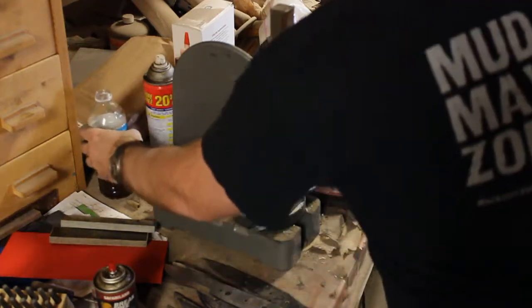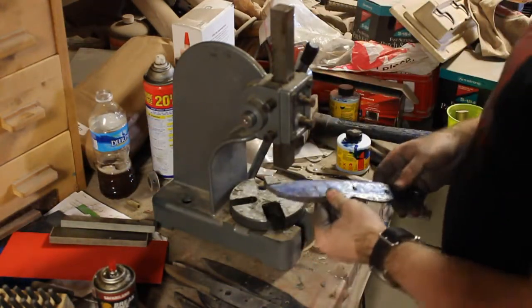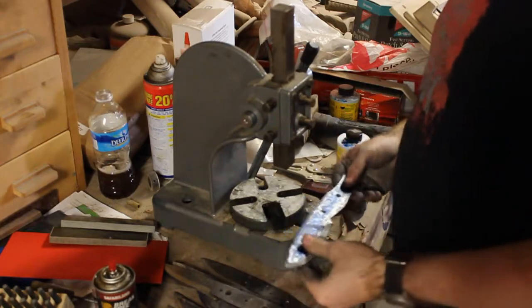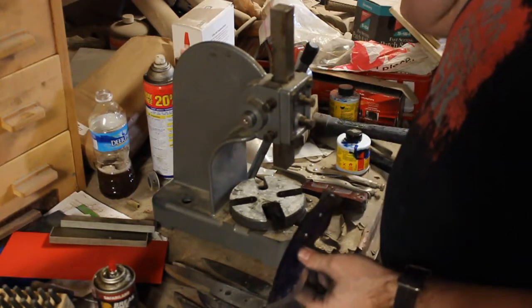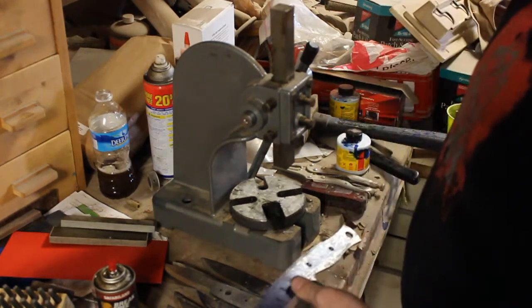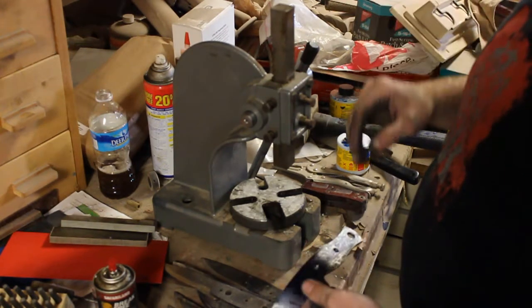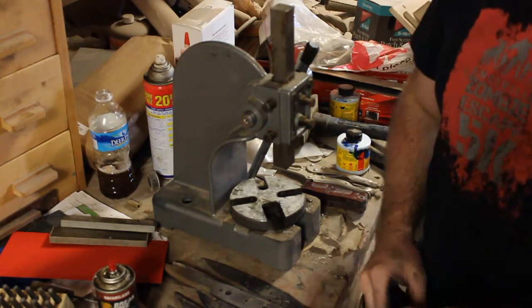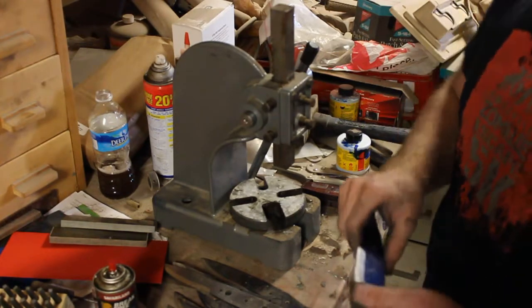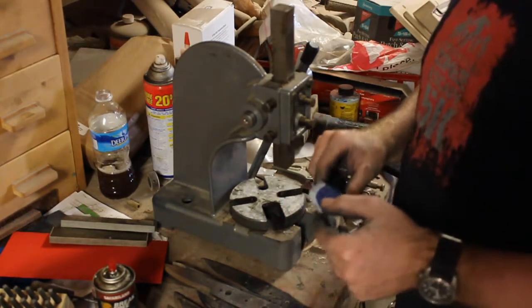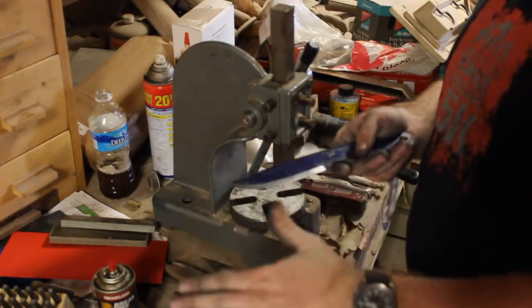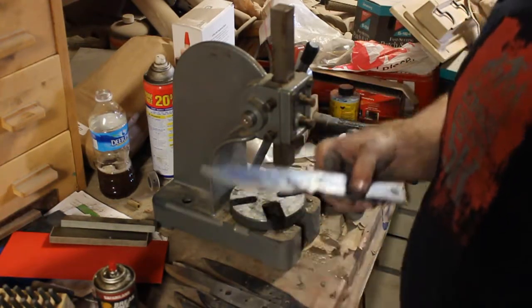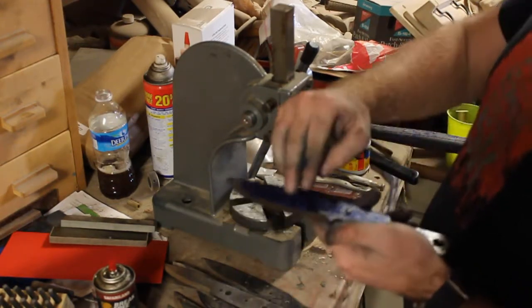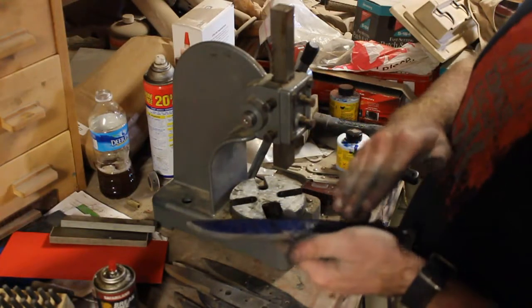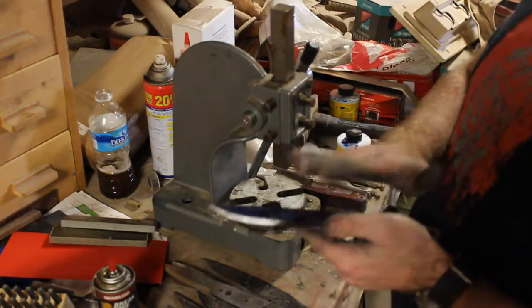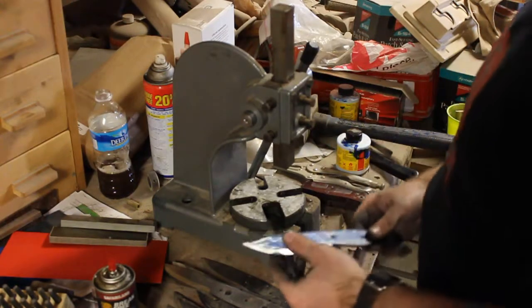Next step, after we've ground our edge prior to heat treat, is stamping your maker's mark. Now, this is only if you're going to stamp. If you're using an etching machine, it's recommended, I don't know by who, but this is just the way that I would do it, that you do your etching after you've applied your finish and before you apply your handles. That way, if your etch doesn't come out correctly, you can sand it off. It's much easier to do before you apply your handles.